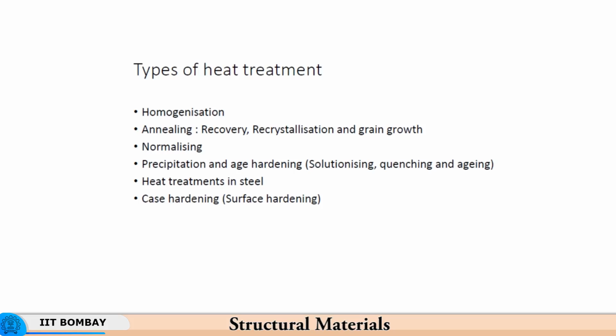If it goes into the interior, the crack does not get initiated because the surface is hard. So, that is why I have some surface hardening treatments where I can selectively change the chemical composition of the surface and generate phases of higher hardness. So, what I do is that on the surface I increase, say, the carbon, for instance, so that now on the surface I have got greater carbon content, in the interior I have got much lesser carbon content. So, for example, in the interior I might have just 0.2 to 0.3% carbon, but on the surface I might have 0.8 to 0.9% of carbon, as a result of which I will be getting a much better structure to withstand the wear and tear that we experience when the gears are operating.